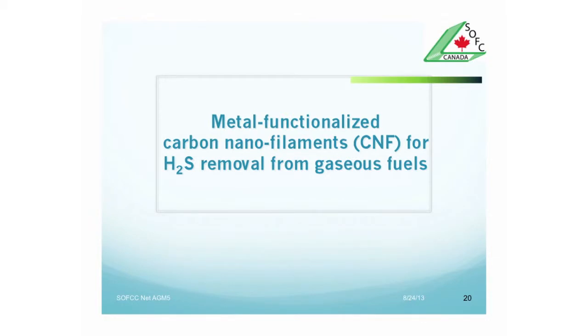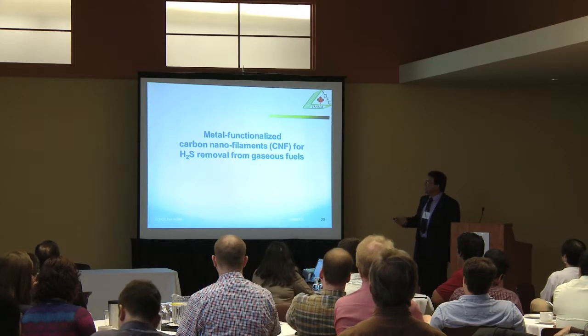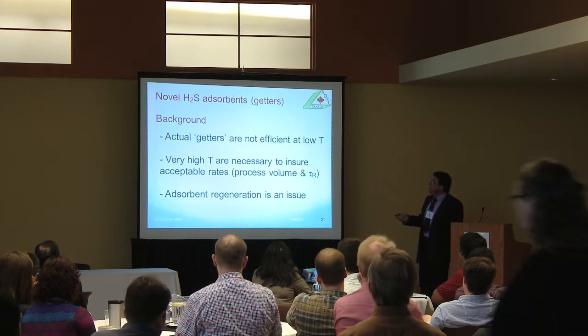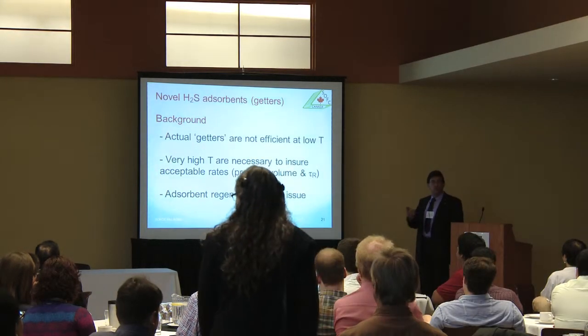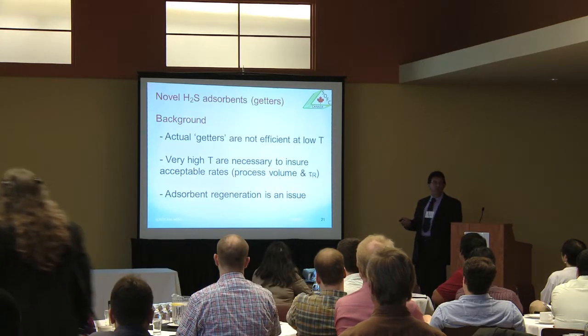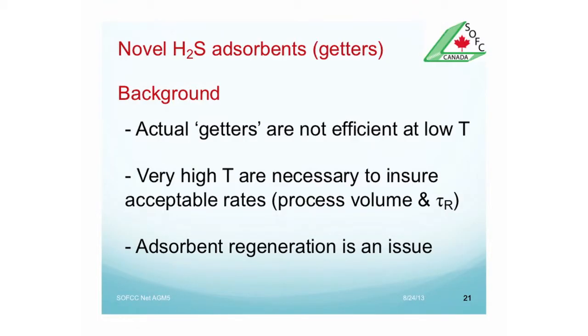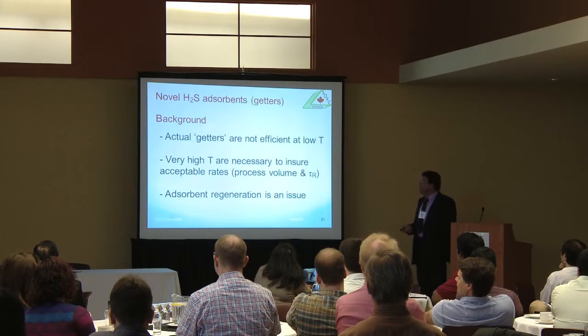So the second thing we have started developing, and are now continuing, is to use metal-functionalized carbon nanofilaments for the hydrogen sulfide removal from gaseous fuels. Why? Actual getters are not efficient at low T. People in the industry know that. We typically have to go over 500 degrees. The very high temperatures are necessary to ensure acceptable rates, which affect process volume and residence time. And adsorbent regeneration is a big issue, not easy all the time.